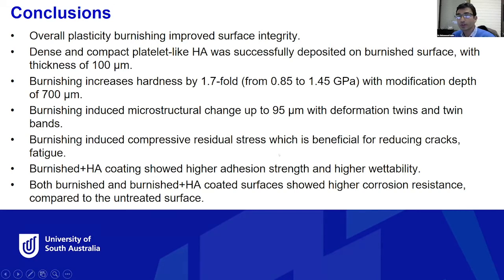Burnishing also induced compressive residual stress that is beneficial for reducing cracks and fatigue and helpful for corrosion protection. And we demonstrate that, overall, the burnished and also the burnished plus HA coating is going to provide higher corrosion resistance, and hopefully this kind of process is going to provide additional resistance, preventing the degradation of the magnesium alloy. So that's the end of the presentation, and thank you very much for your time.